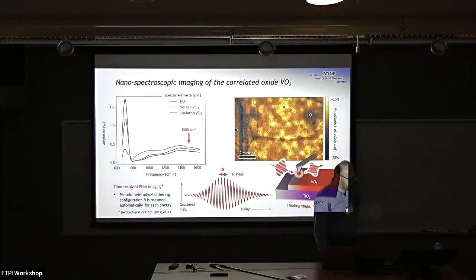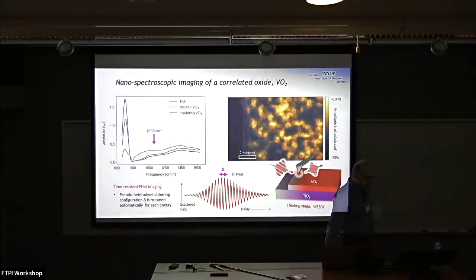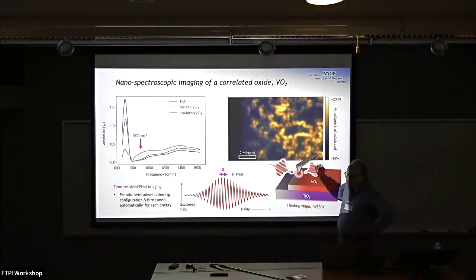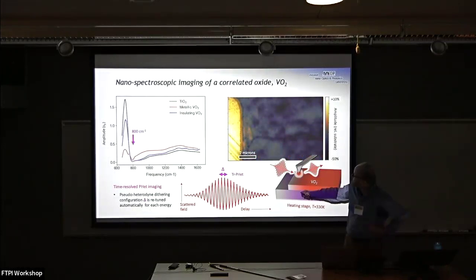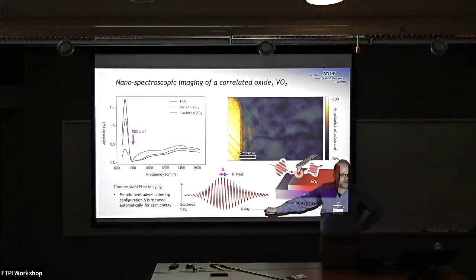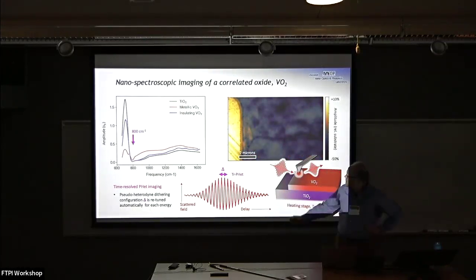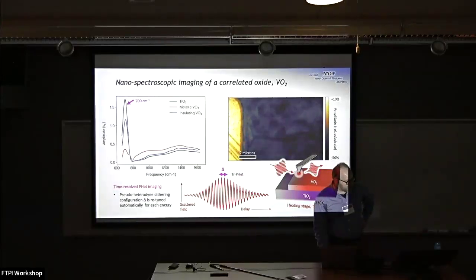So using our pulse laser, we can tune the energy of the laser and map the optical conductivity of this correlated metal. It's poised right in the middle of its insulator metal transition, and we can see which regions have a strong reflectivity and which regions have a low reflectivity, and even tune so far down that we tune to the optical phonon associated with VO2. And here we can see a contrast in the optical phonon of the VO2, particularly between the metal, which is now dark, and the insulator, which is now bright. The metal screening basically the response of the phonon there.